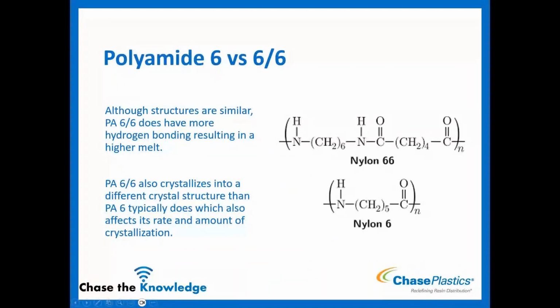Okay. The question that we probably get most often when we talk about nylons now is going to be 6 versus 6.6. They're very similar in the amount of carbons, 6 of them, between your groups. So overall, what is the difference? What do I say is a big enough difference between them that I'm worried about it? So the first thing to know is that although the structures are very similar, 6 carbons, 6.6 does have more hydrogen bonding, resulting then in a higher melt. And so more bonds, higher melt, higher temperature it has to get to melt and break them apart. 6.6 is the higher heat of the two.